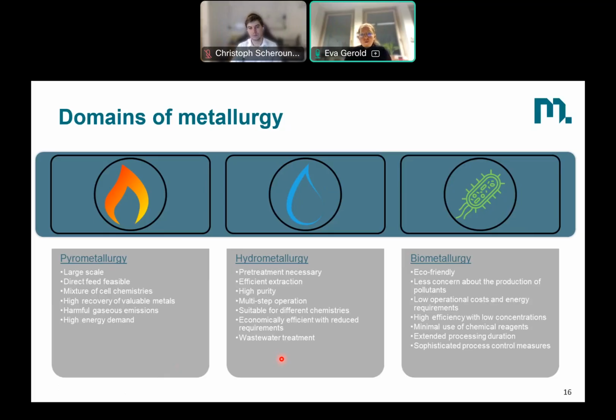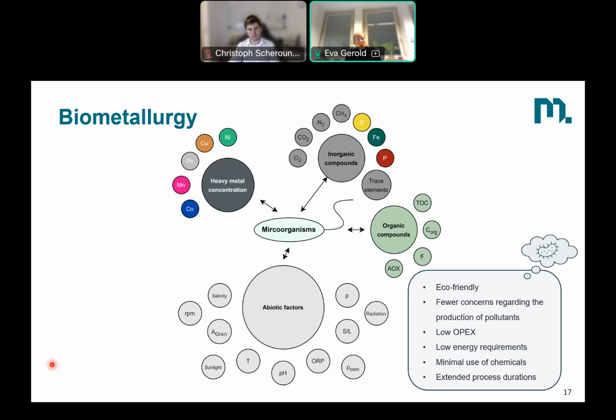This is quite an eco-friendly form of metallurgy. There is less concern actually about the production of any pollutants, because we always have quite low concentrations of acids, low concentrations of polluting agents. We have quite low operational costs and energy requirements because you have quite low temperatures, like 25 to 26 degrees C. There are high efficiencies of recoveries possible with low concentrations of acids actually, and a minimal use of additional chemical reagents. Of course, you have extended processing duration with bacteria, and also a sophisticated process control measurement, because you need to keep your bacteria at a specific environment.